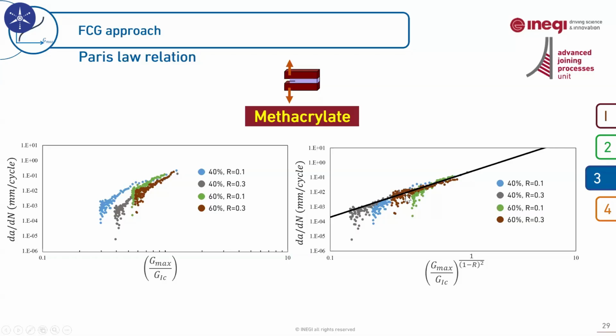And using this curve, you just need to analyze, probably numerically, the energy. And by knowing the loading condition, you will be able to know what's the rate of crack growth for all these loading scenarios. So you just need to test one of them, and then you can precisely predict the dA over dN for the other three. That's also very important when we characterize adhesives in terms of fatigue crack growth. We need to try to take into account the effect of all important parameters to be able to construct this master Paris law curve.